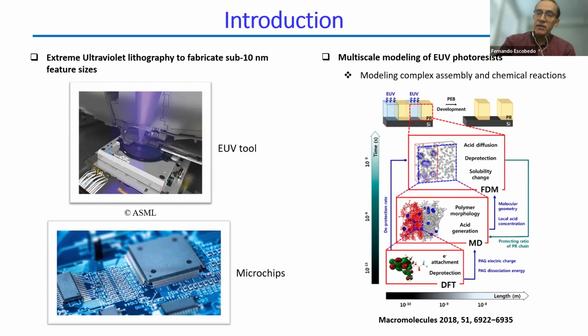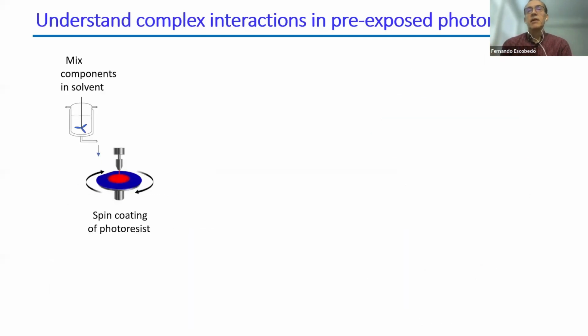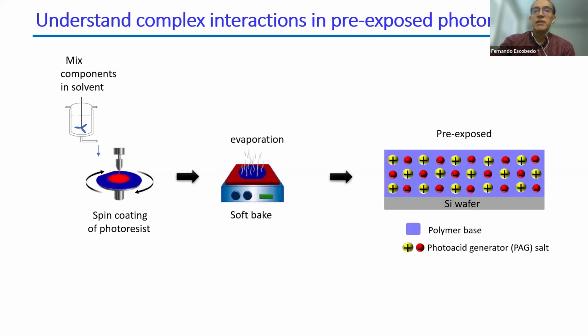And what we wanted to do was focus on what happens before that, because there was clearly something missing there. Just to remind you, the way these things are made is that you first mix components in a good solvent, then you spin coat it onto a substrate, then you evaporate the solvent, and you end up with basically the polymer base. There are two key components to this material. One is the polymer itself, and then you have this photoacid generator, or PAG. We'll just be calling it PAG, which is a key ingredient in the way this is going to be processed, that we'll show you in a moment.